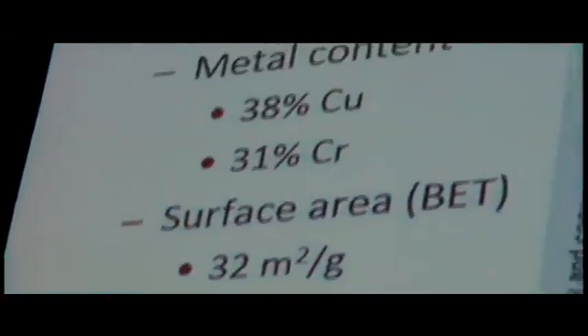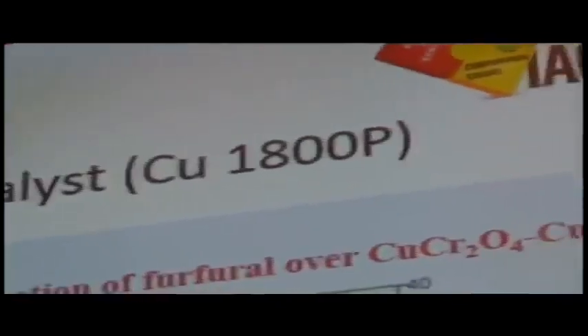First of all, we see that some of the chromium doesn't stay put where it is. It tends to creep over the catalyst, and we see actually the formation of a lot of copper chromite on the external surface area, not touching the chromium oxide. In addition, the little squiggles you see here are carbon deposits that build up on this catalyst over a long period of time. So the goal of this group in IAC was to find other ways of stabilizing these particles to decrease the amount of deactivation.